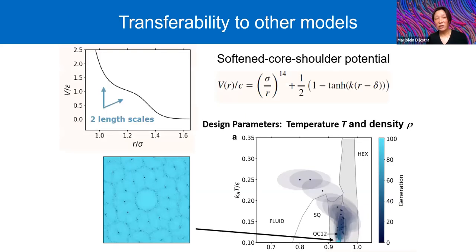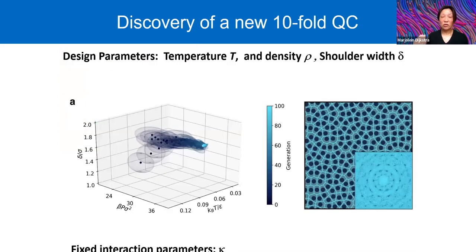We then investigated whether we can also transfer it to other model systems, for instance, a system where the particles interact with a softened core shoulder potential. And also in this case, if we want to inverse design a 12-fold quasicrystal, it is able to find this 12-fold quasicrystal. And this is just the phase diagram from literature where we really confirm that there's a 12-fold quasicrystal. We can also ask it to find a new quasicrystal in this case that wasn't investigated for this system before. And here we really discovered a new 10-fold quasicrystal for this system.